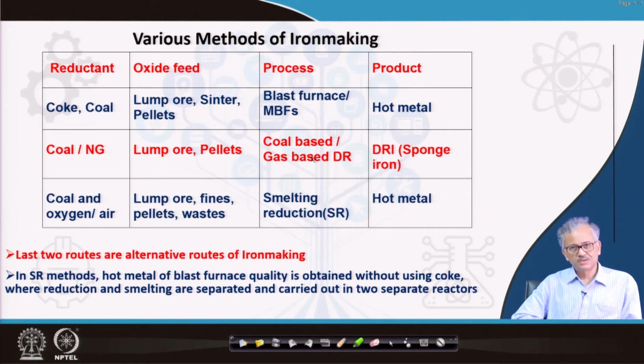That is called the coal based DR process. In this coal based DR process, the reductant gas CO is generated in situ because of carbon gasification. Whatever CO2 is generated by iron ore reduction gasifies the carbon, forming CO gas. That CO directly reduces the iron ore, and since carbon is directly participating in this reaction through the carbon gasification reaction, this reaction is called direct reduction. We have talked about that.